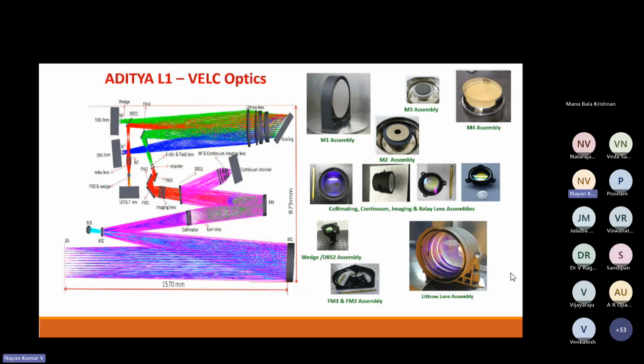But we could attain roughly 0.8 to 1 angstrom. That is the measurement repeatability we have seen. But they demanded different spatial scales also. This was for a 10 micron by 10 micron strip, and taken at several places. We had nearly 36 measurements at different locations of the mirror, as well as